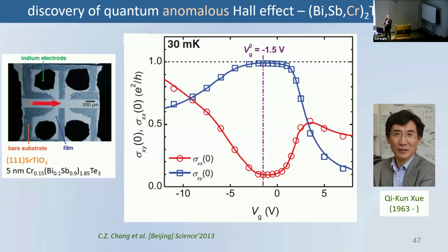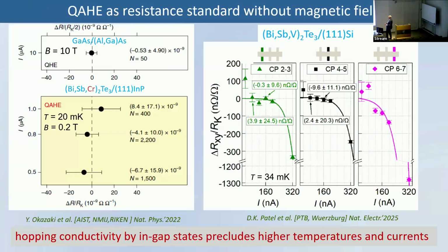So this quantum anomalous Hall effect produces zero magnetic field, non-zero magnetization, but zero magnetic field produces very nice quantized value. And people started to make a resistance standard of that. Here are measurements in 10 Tesla for a standard quantum Hall effect device. And if you measure 50 times, you have this kind of scattering between data. Here you have to measure for quantum anomalous Hall effect.